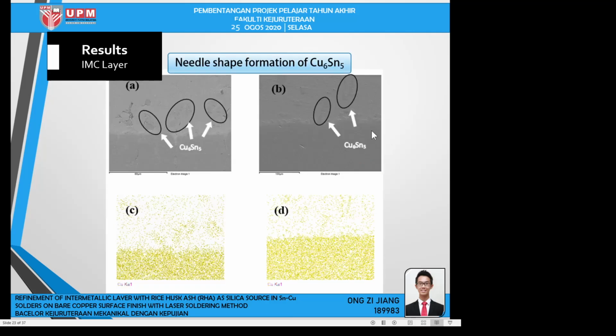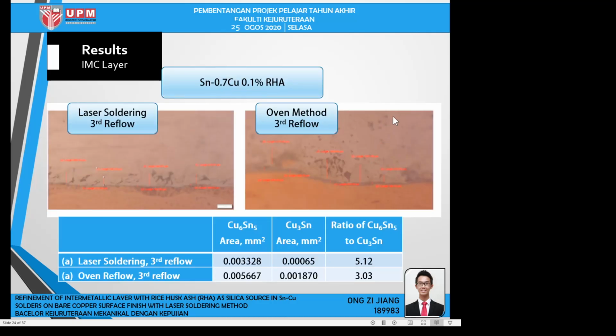We can also observe the needle-shaped formation of the Cu6Sn5 through the area mapping to observe the copper element from the IMC layer. In figures C and D, we can observe the copper elements of the Cu6Sn5 to confirm that there is needle-shaped formation of Cu6Sn5. And then for the IMC layer thickness, this is the comparison of the area as well as the ratio of the Cu6Sn5 to Cu3Sn of the laser soldering and oven reflow for the third reflow.